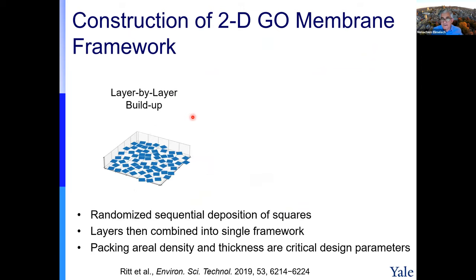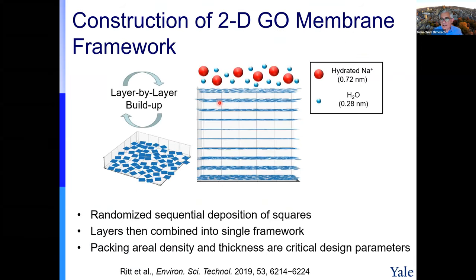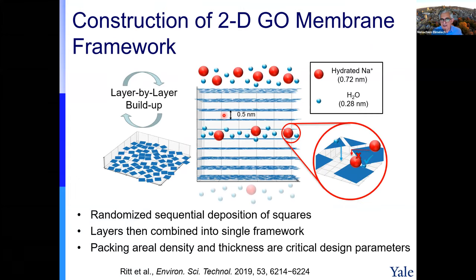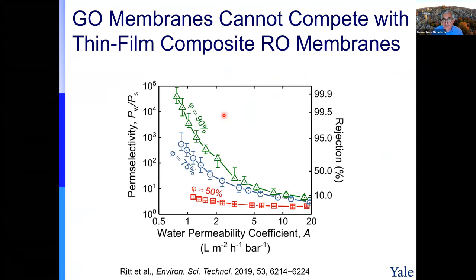And I did not mention it here, but we have the spacing here. We designed the spacing to be 0.5 nanometer, which is very challenging. And again, we assume that all the spacing of all these nanosheets that are deposited there will be 0.5 nanometer, which, again, probably it's a dream. But even with this, as you have 90% coverage, we get more and more rejection and we stop at about 1. Again, if you go to very, very low permeability, you can get 99% rejection.